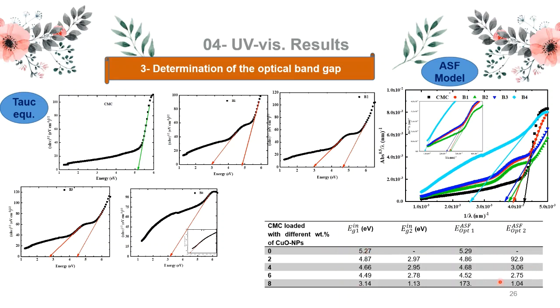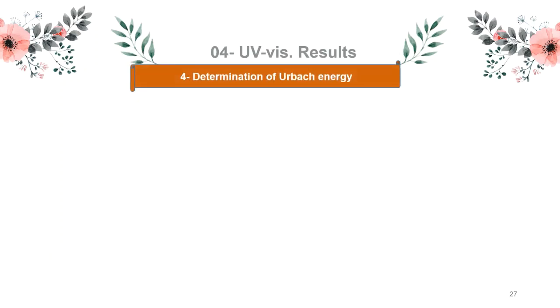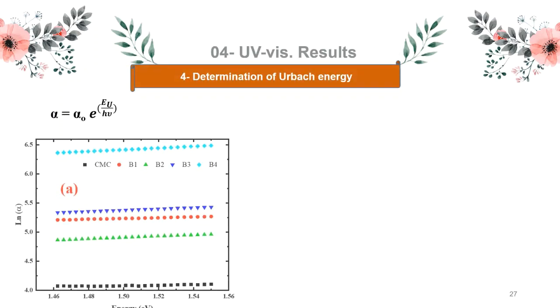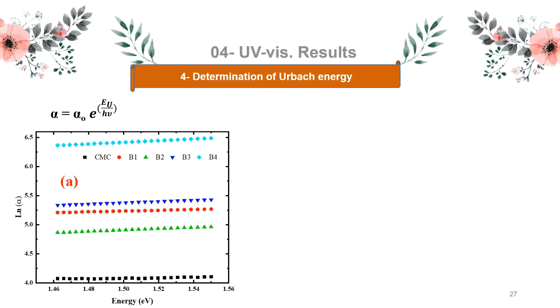On this concern, the addition of copper oxide creates localized states inside the band gap, and the transition between such states results in a band gap value less than the HOMO-LUMO band gap. We determine the value of the Urbach energy using this equation in order to specify the width of the localized states within the forbidden gap.